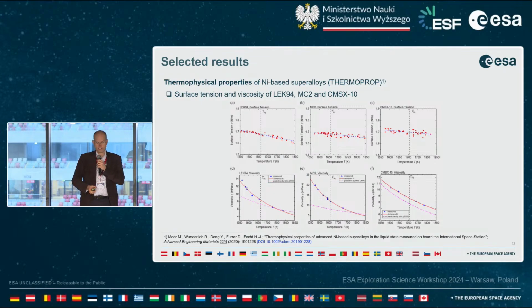So next, I'd like to give you some examples, results that were obtained over recent years. The first one is on thermophysical properties in nickel-based superalloys. It's related to the ESA-AO ThermoProp, where colleagues looked into surface tension and viscosity of different, commercially available alloys. And what is interesting is perhaps the lower set of figures, where you see a comparison of viscosity as a function of temperature, and the solid line is an Arrhenius fit to the data,